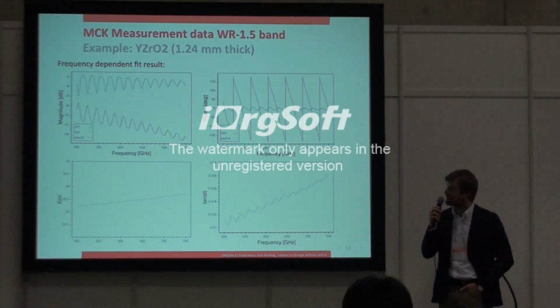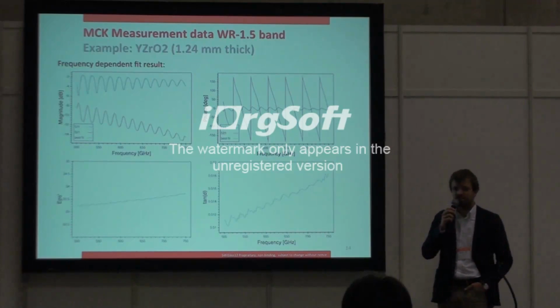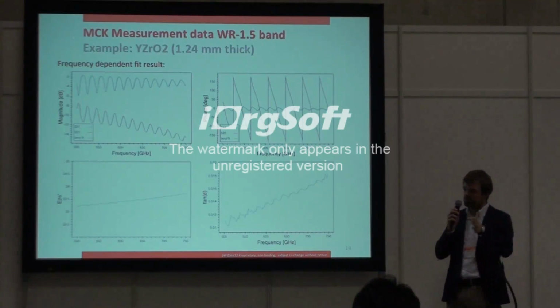One example of this is a rather exotic material that we call yttrium-doped zirconium oxide. It's a very hard ceramic. When measuring this material, first of all, we see it's a very high permittivity material. It has an epsilon on the order of 33. But it also has frequency dependence in its permittivity characteristics. So we see that we have an epsilon and a tan delta that increases with frequency. And to achieve these results, we use a second model in our software, which for each frequency point will take the measured S-parameter data and compute the according permittivity.